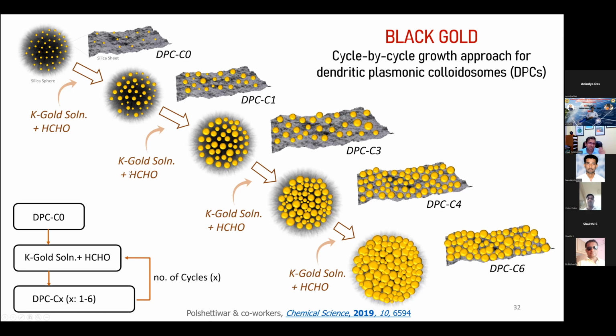Then in the second cycle of nanoparticle growth, we tuned the concentration of gold atoms by reducing the gold precursor with formaldehyde. The concentration of gold atoms is below supersaturation, meaning the gold atoms will not undergo nucleation and growth on their own - they won't form new nanoparticles by themselves. Instead, these gold atoms will grow onto the existing gold nanoparticle because of the better wetting factor of the gold atom onto the gold surface. That way you can slowly increase the size of these gold nanoparticles.